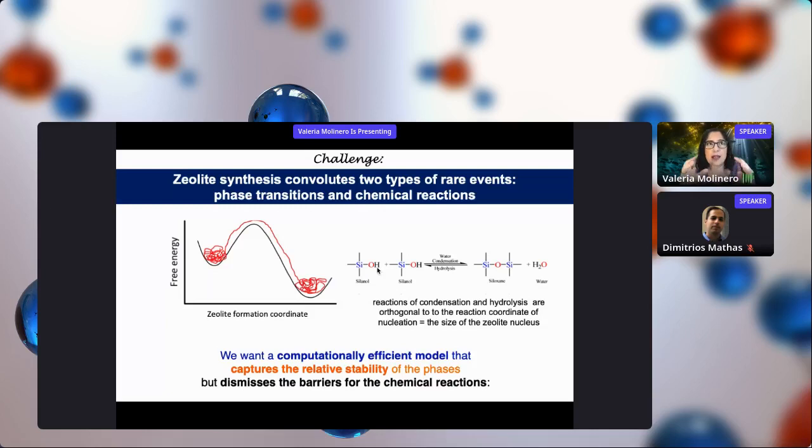If we consider silica without any water, you can only make it mobile above the glass transition at about 1200 centigrade. Now, the zeolites are synthesized at temperatures below 200 centigrade. So the way that you have to really reform the silica-silica bonds is to have water and a very high pH to enforce the condensation and hydrolysis of these bonds, which is the prerequisite for the transformation of the network.